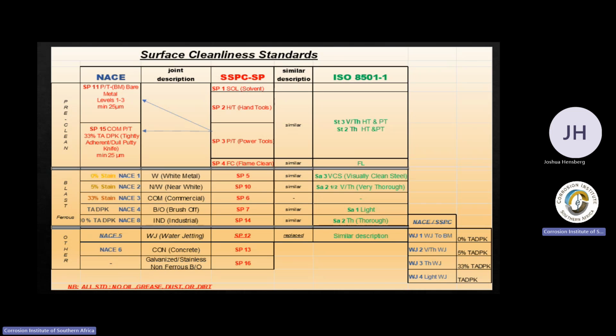And again, that's where the time factor comes in with a lot of these. When you clean that surface, once you've cleaned it with the water and it dries, or once you've blasted the surface, you need to remove the dust. And the most effective way to remove dust off a surface is vacuuming. You actually take a vacuum cleaner and vacuum the surface to get the dust off.